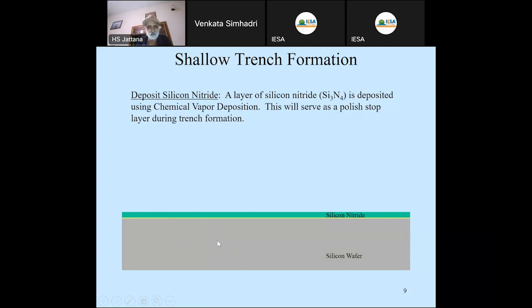In the rest, there can be some impurity, some oxygen, some carbon atoms, 10 raised to the power 11 per centimeter cube might be there in the lower part. But in the top, it has to be absolutely crystalline, 100, no impurity at all. Otherwise, it will affect your processing, it will affect your yield. Because processing steps like etching, thin film deposition and growth like oxidation are dependent on the crystal orientation plane also. So in a CMOS, as you are aware, we are using 100 orientation wafers.